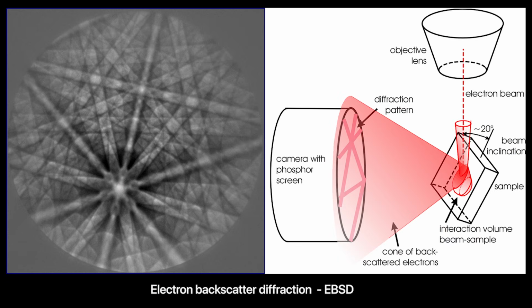Then we verify that by going to a scanning electron microscope and using a technique called EBSD, electron backscatter diffraction, for different crystallographic orientations. The electron beam falls on the sample, and there is a detector which detects the backscattering of the electrons. Based on the crystallographic orientation at that particular location, it will tell you. So you do it for the whole sample. It should be the same, right? You scan over the whole sample, and then you stitch all the colored images.